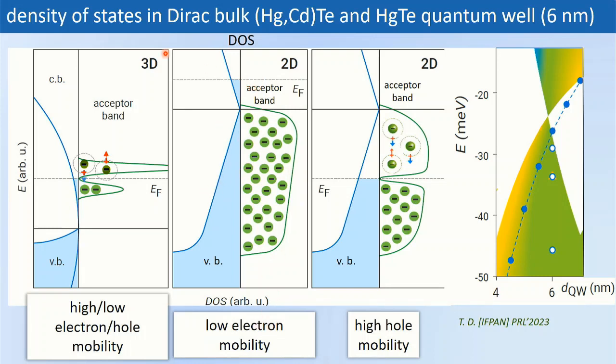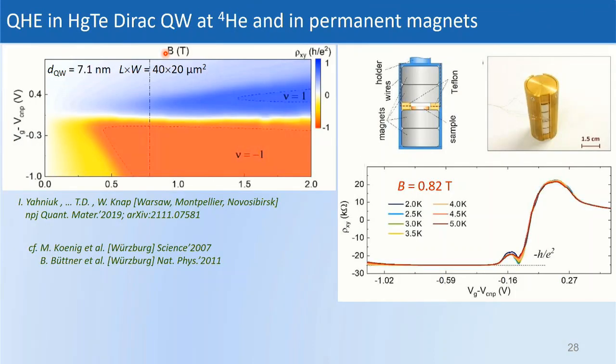And now we measure the Hall effect. We have the Hall effect for electrons. But if we change the gate voltage and go to holes conducting, if we put the voltage to have more holes, we see that this plateau starts at lower magnetic field compared to electrons, because there is very beautiful physics: if we have degenerate acceptors within the bands, there is ordering between these acceptors, a Coulomb gap, and so on, and altogether this gives higher mobility in the case of resonance states.